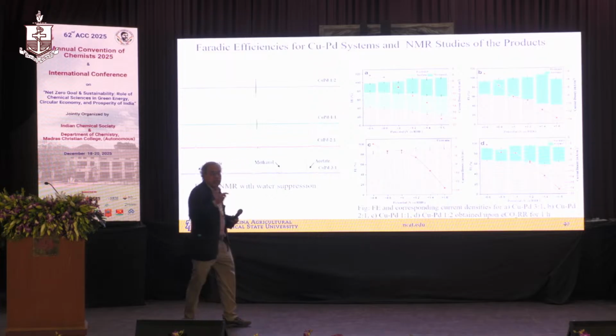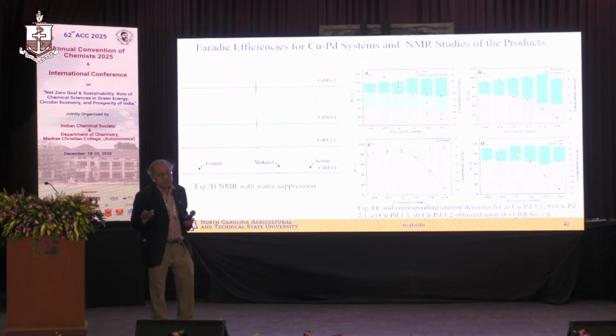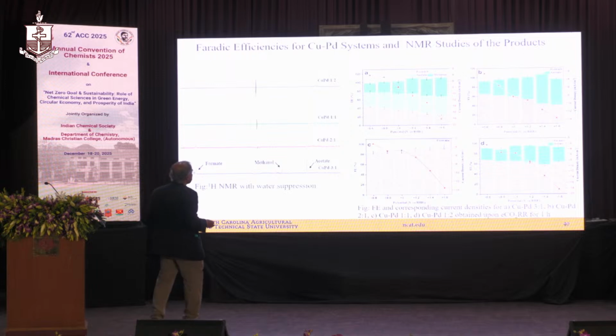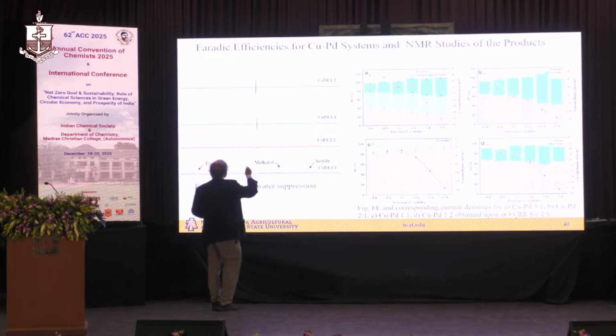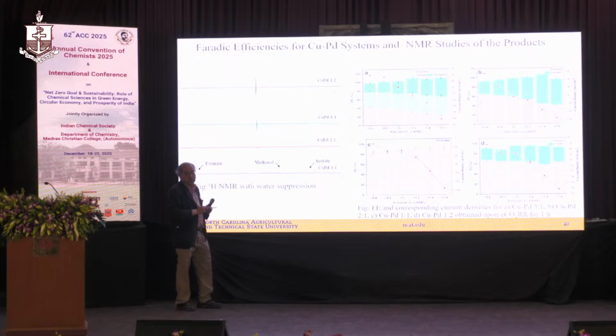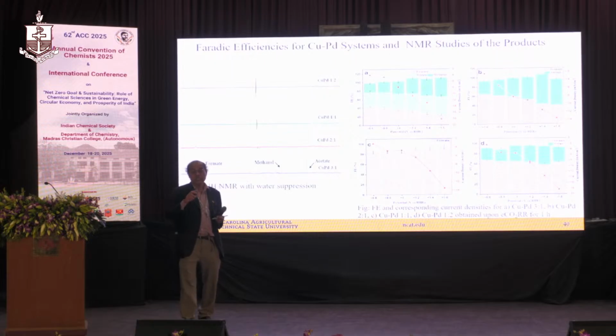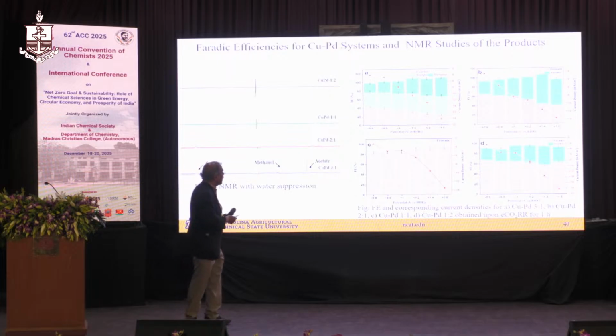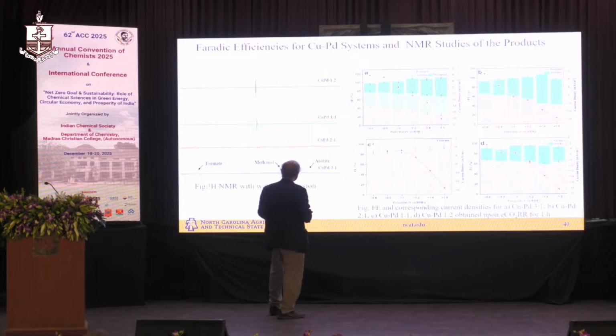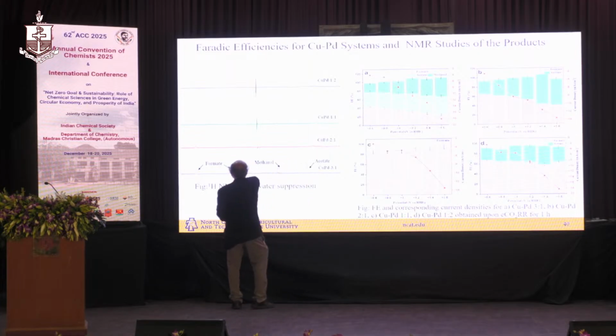Then you analyze the products using NMR. Okay, and what you see is that when you use 1-to-1, you only get formate, very selective. And we did not see hydrogen production, because hydrogen production is the major issue where the Faradaic efficiency decreases. So this was really, really exciting for us. We have actually filed a patent application on some of these. And then you can see, if you go to 3-to-1, you can make not only formate, but methanol and acetate.